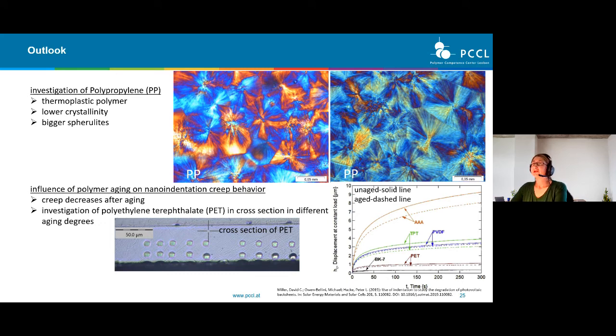What I also want to do is to investigate the influence of polymer aging on nanoindentation creep behavior. You can see here on the right side a picture from literature where we have aged and unaged samples. The aged samples are the dashed line and the unaged samples are the solid line. You can see that the creep curves are decreasing after aging. I want to investigate polyethylene terephthalate (PET) in cross-section in different aging degrees and compare these to each other.